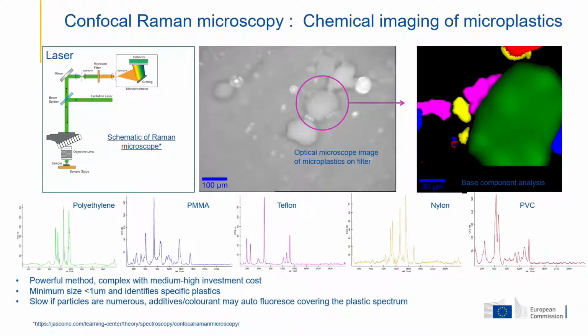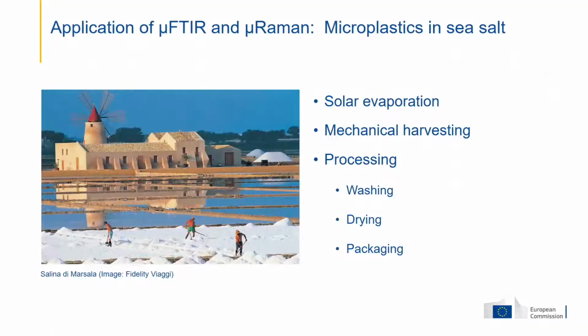This is a powerful method, but it's complex and has a fairly high to medium investment cost. It has the advantage of having a lower detection size than FTIR, and is very useful for identifying specific plastics. Unfortunately, the method is fairly slow, and in some cases, the presence of additives or colorants may result in fluorescence, which completely covers the spectrum, making it impossible to identify the material.